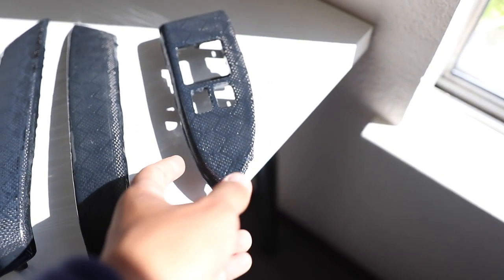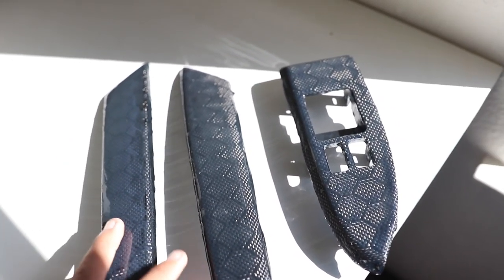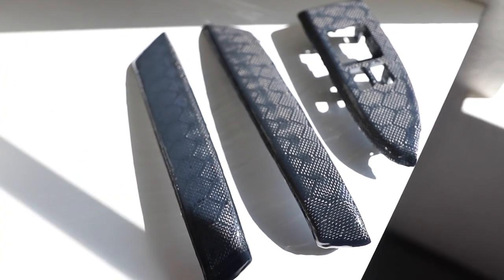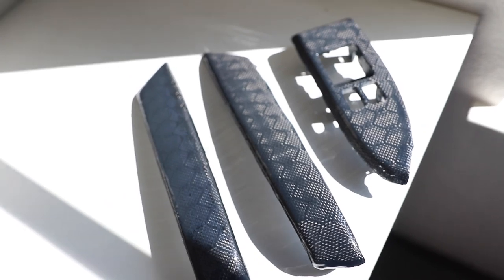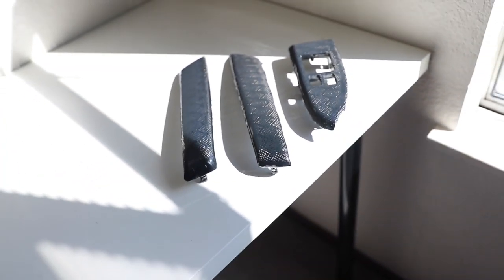Videos I'm going to post right now you guys will see all I did and how I pretended to know what I was doing. After I messed up the other part, I knew exactly what it had to be — it had to be a dry sticky, kind of like a sticker sticky. You touch it, it's dry but it's sticky — that's exactly how it's supposed to be. And I figured out you're not supposed to sand in between coats. You're supposed to put the resin on top, let the bubbles happen, then once it's cured put another layer of resin — less bubbles will rise. You still do the heat gun, and then boom, the final third layer of resin. It will leave it spotless, without bubbles, no nothing. That's the way you're supposed to do it. I'll put the steps in the description below so you guys can follow that method.